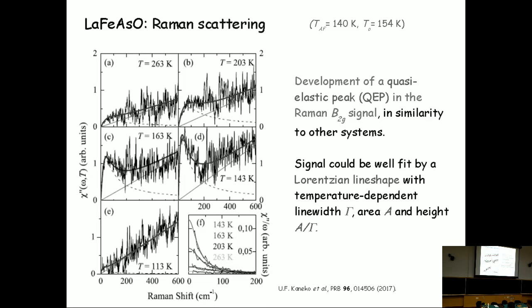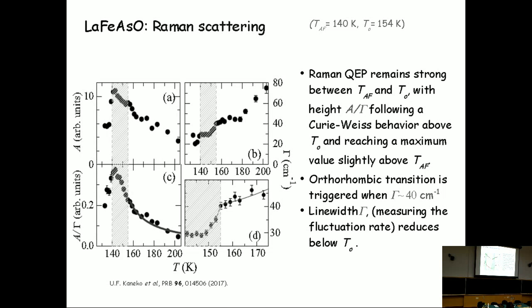So we can fit this signal with a Lorentzian, and from that we get the area and the width as a function of temperature. And that's what we have. We plot the area of that nematic peak as a function of temperature, and then you also have the width of that peak as a function of temperature. From the area and the width, of course, you have the height, which is the area divided by the width.